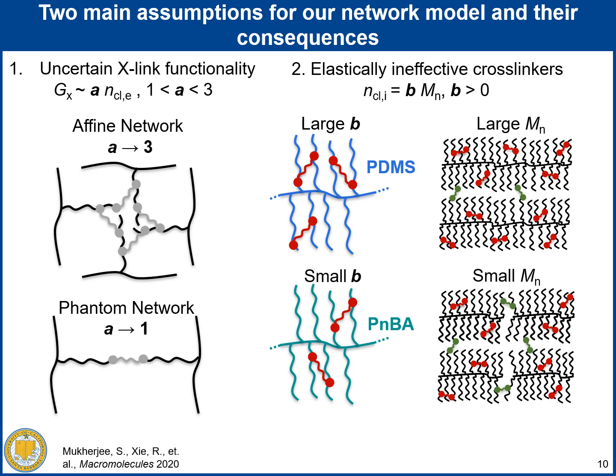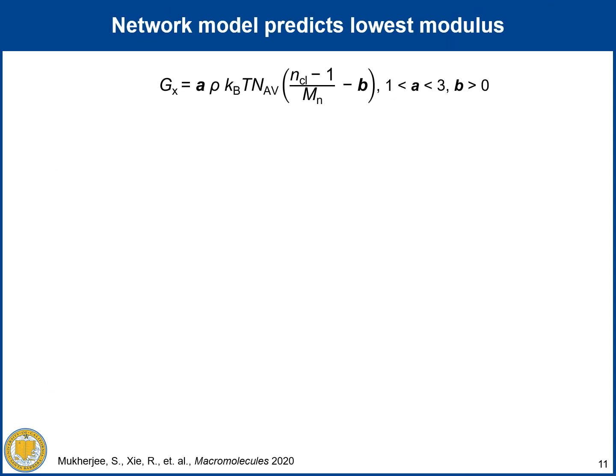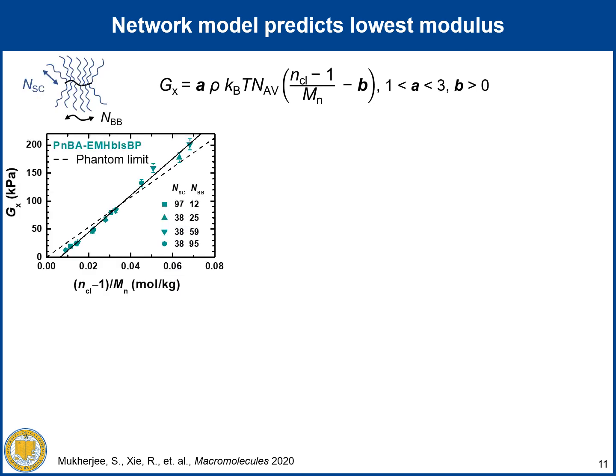After some calculation, we can simplify the relationship between the network moduli and the added crosslink loading with two fitting parameters A and B. To validate the proposed model, we have determined the network moduli for a range of different Bottlebrush polymers and crosslink loading. The dashed line is a phantom network model, assuming all crosslinks are elastically effective. The solid line is the best fit of the data using our proposed model. The fitted parameters are summarized below.